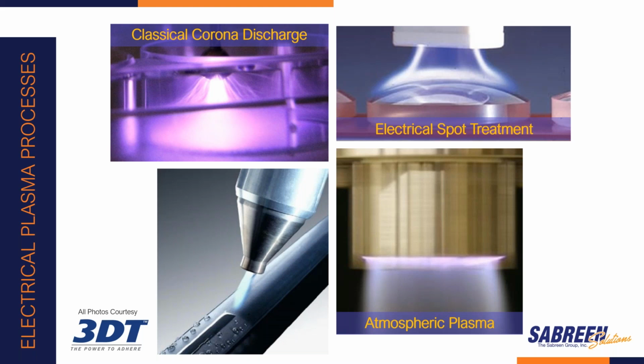Classical electrical corona discharge uses a generator and electrodes connected to a high voltage source, a counter electrode at potential zero, and a dielectric used as a barrier. A high frequency, high voltage discharge step-up transformer creates a potential difference between 2 points requiring earth ground, usually at about 35 kV and 20 to 25 kilohertz. Classical corona discharge is a very good surface cleaning process. Ozone is produced.